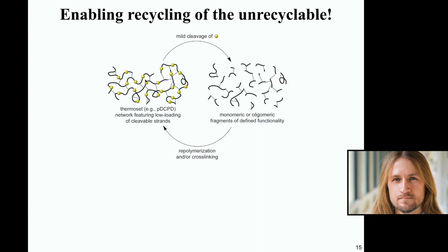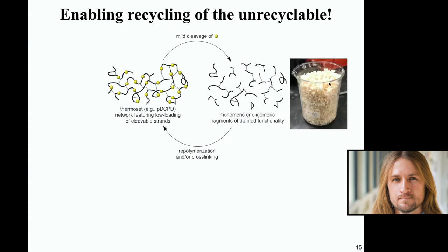Well, here I show you in cartoon form a pDCPD network of these cross-linked macromolecules that have these yellow spheres, which are our cleavable silyl ether linkages. We can take this material under very mild conditions, cleave these yellow spheres to generate oligomeric and macromolecular fragments that we can simply take, and here's an image of a beaker filled with this material, and simply re-expose it to the conditions used to form pDCPD in the first place and generate recycled samples, which have properties that are equivalent to, if not even improved, compared to a new sample of pDCPD.